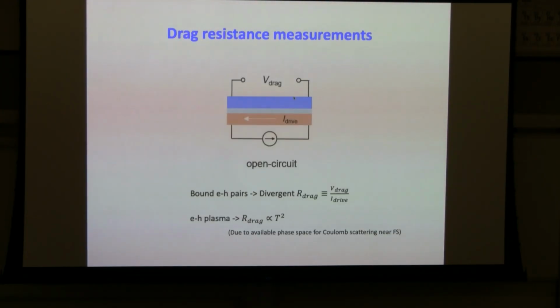Okay. So we can study this Mott transition a bit more carefully by doing another experiment. In this case, we still drive a current in the electron layer, but just measure the voltage in the hole layer in an open circuit. This is called a drag resistance measurement. You flow current in one layer, but measure the voltage in the other layer. So the drag resistance is the voltage in this layer divided by the drive current in the other layer. If you have a bound electron-hole pair at low temperature, you will just get infinite resistance, because this is an open circuit, the holes are not allowed to move, and as a result, you cannot drive a current in the electron layer. So you just get infinite resistance.